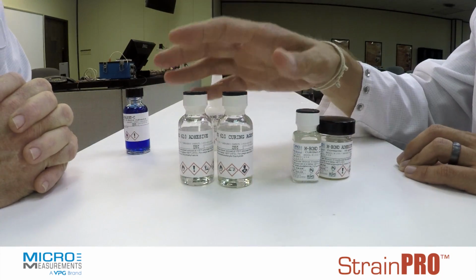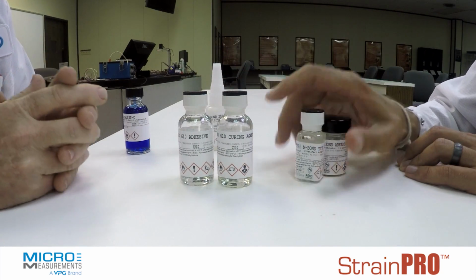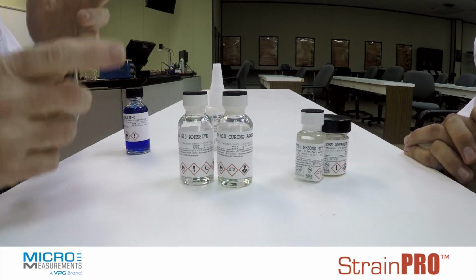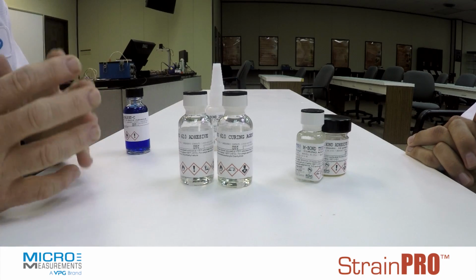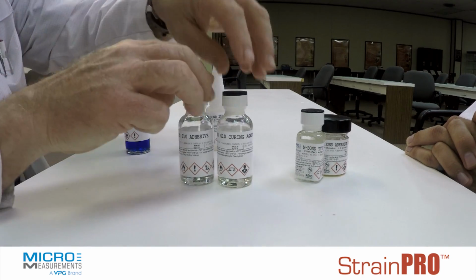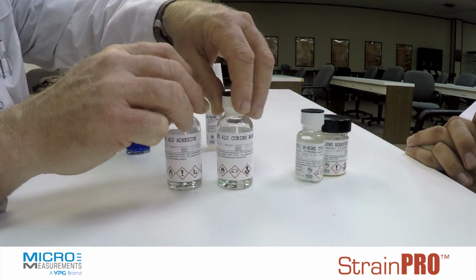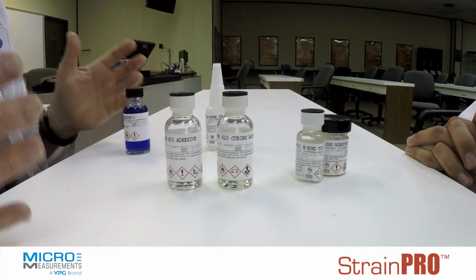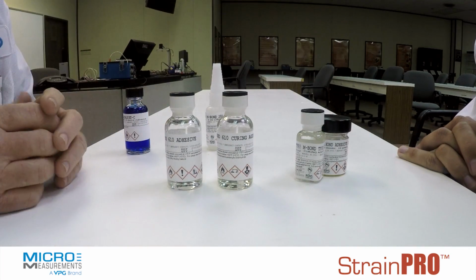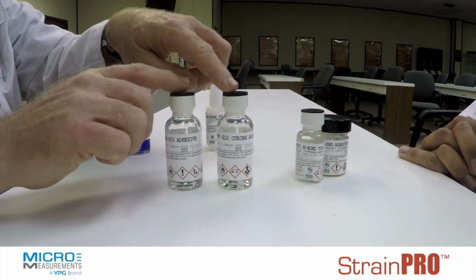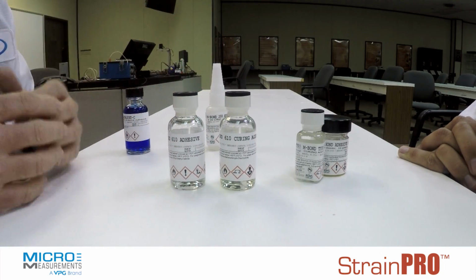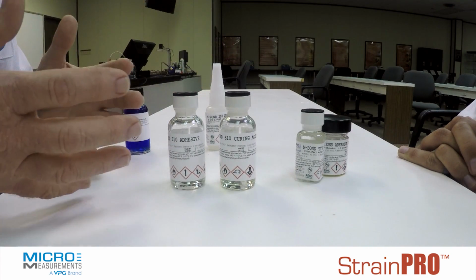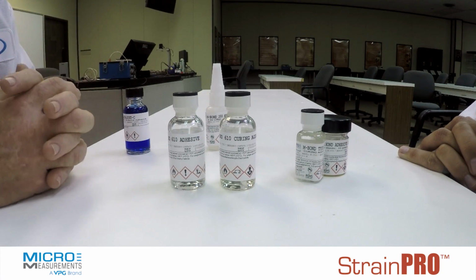Awesome. So you think you could even use something like our solvent thin epoxy, M-Bond 600 or 610 afterwards, after we filled it in with the epoxy? You could. However, the AE10 and GA2 are limited to around 200 degrees Fahrenheit, while the 600, 610 adhesive systems are rated much higher. So if you're within the temperature range of the AE10 or GA2, certainly you could use this on top of it, but it would probably be a redundant component, something overqualified for the job.